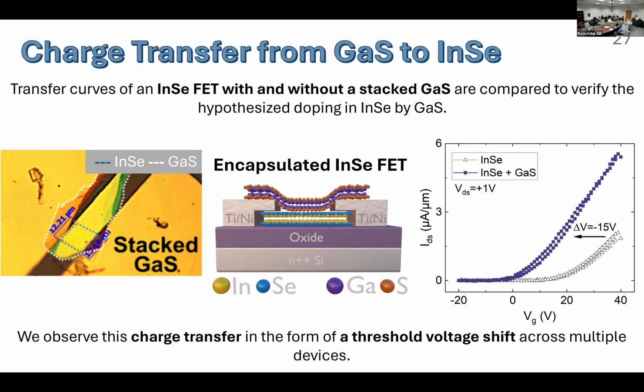And I've actually created different devices where it is not touching the metal pads, where it's exclusively in the channel, and we still see this effect. So that's what led me to believe that it's not the conduction through the gallium sulfide that is causing this. And we also measured just the gallium sulfide device alone. Yes, and it's very resistive. The current is in the order of 10 to the -4 microamps, so that is hundreds of picoamps. So very low. That's what led me to believe that there's no current flow through the gallium sulfide.